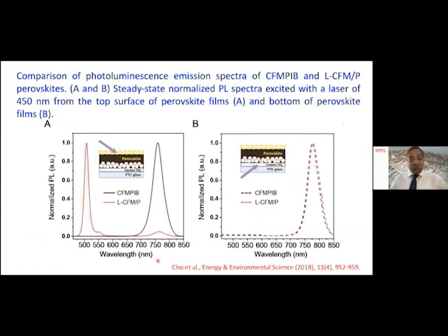Now, how can we prove this additionally? So here, the photoluminescence spectra. We have taken here the first configuration, the mesoporous perovskite NIP configuration, 3D perovskite followed by two-dimensional perovskite. Now, when we interrogate from the top side using a 450 nanometer laser, what you see is emission coming from the two-dimensional perovskite, just follow the red line, and there is a small bump around 760 nanometers. The laser light is not only exciting the two-dimensional perovskite, it is also exciting the three-dimensional perovskite, giving this red emission at 760 nanometers.